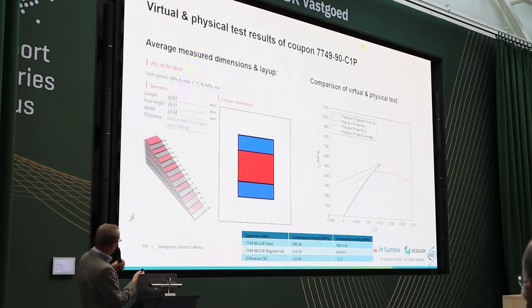On the right, you see the comparison between the test results and the simulation. So I should explain which signal is which. The blue and green lines are the outputs from the strain gauges, because on the horizontal axis is compressive strain from the strain gauge, and on the vertical axis you have compressive stress, nominal stress. And the black line is the average of the two strain gauges.